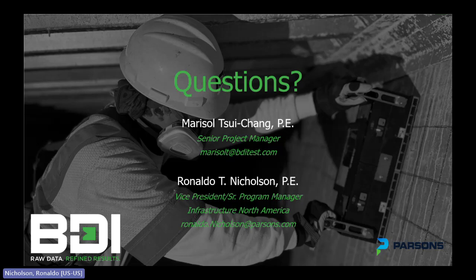That was based on our models and what was needed. I guess the fine difference between what was needed to confine the ASR expansion and the additional weight imposed on the piles due to the encapsulation system. As I said, we were teetering on the limits of the pile capacity based on current LRFD codes and what we needed to have sufficient forces to counteract the further expansion of ASR over time.